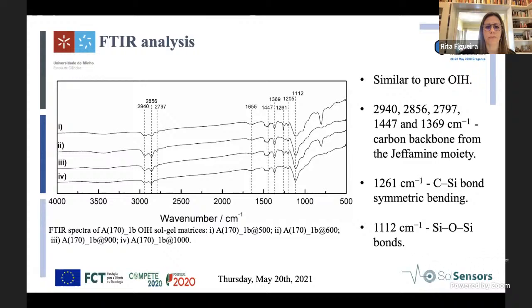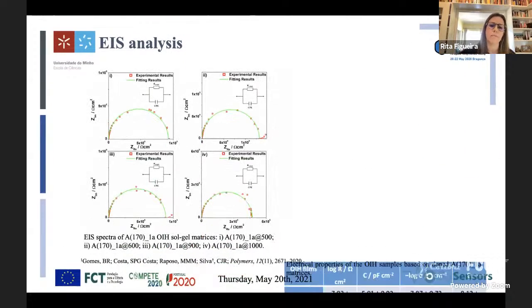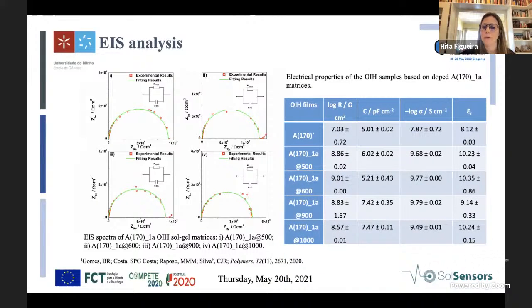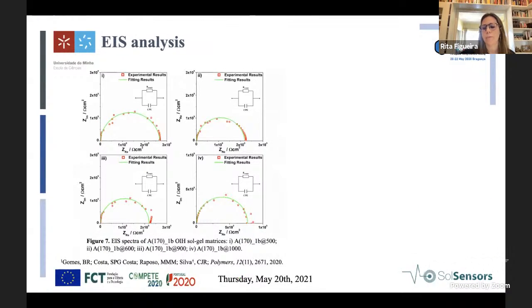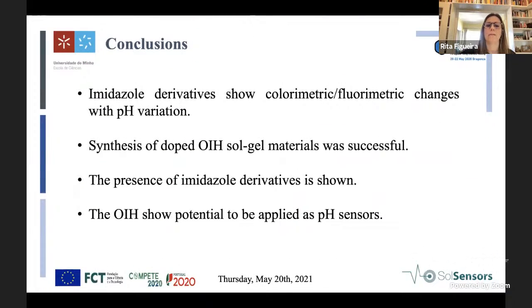I will not go further into this because I have something more personal that I want to share about Professor Carlos, for those who knew him before. And if you want to know more about our project, you can contact me. We always performed the same studies. We performed electrochemical impedance and FTIR, and we concluded in the end that the imidazole derivatives showed colorimetric and fluorimetric changes. The doping of the hybrid sol-gel materials was successful, and the presence of imidazole derivatives was shown. And they have potential to be applied as pH sensors.